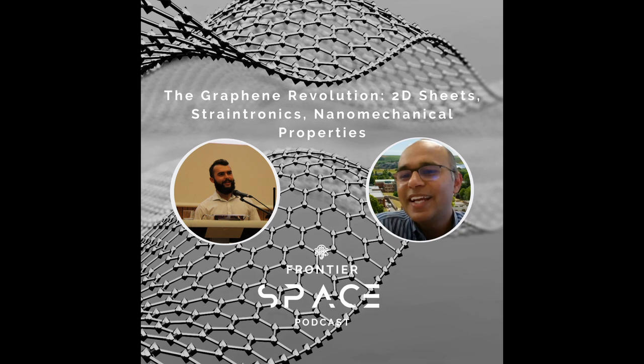Another thing we have to be careful about is that straining does not necessarily improve the property of the material. As I said, when you have a proper pristine flat material and you stretch it, it changes. The change is required here, not the improvement. Graphene itself is a very superlative material with very high conductivity. So a slight change can give more applications rather than improving it. If we really want to improve it, just remove the defects. But sometimes the changes are required for selectivity. So here comes the question of the role of the grain boundaries, which I'll come to a bit later.